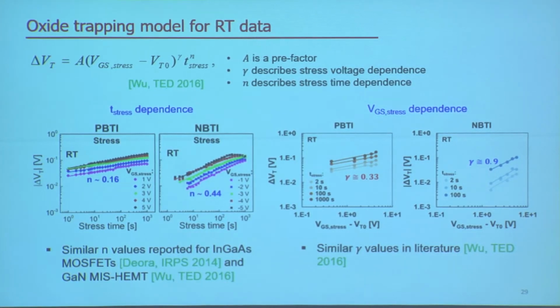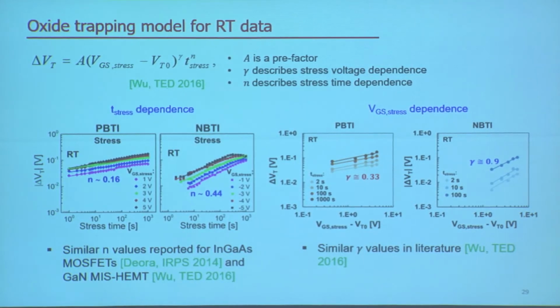And our experimental data yield an N value of 0.16 for PBTI and 0.44 for NBTI. So these N values are very similar to what people have reported for InGaAs MOSFETs as well as gallium nitride MISHEMT devices. On the right-hand side, we studied the VGS stress dependence, and we got a gamma value of 0.33 for PBTI and 0.9 for NBTI. So this gamma value is also similar to what has been reported for gallium nitride MISHEMTs from other groups.